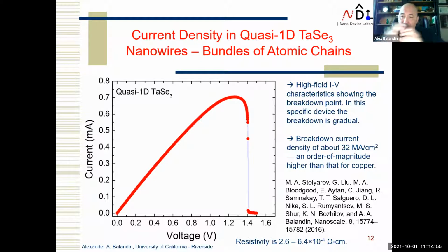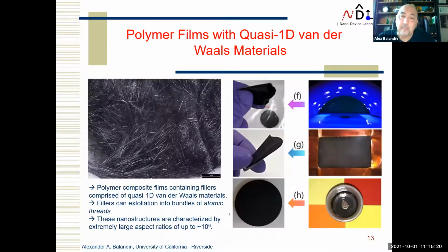So when you scale it down to very small dimensions, resistivity is not increasing very high, like in case of copper or other elemental metals. So in principle, there's a hope to find another quasi 1D material which would have high breakdown current density and simultaneously low resistivity. And I think that would be a big deal for the electronic industry that is looking for new materials for interconnect. We also demonstrated the use of such quasi 1D materials in composites for electromagnetic interference shielding.